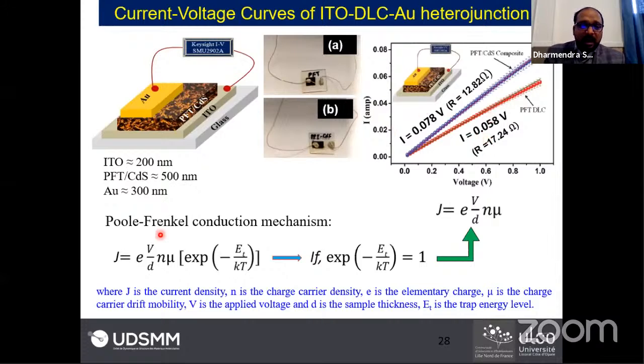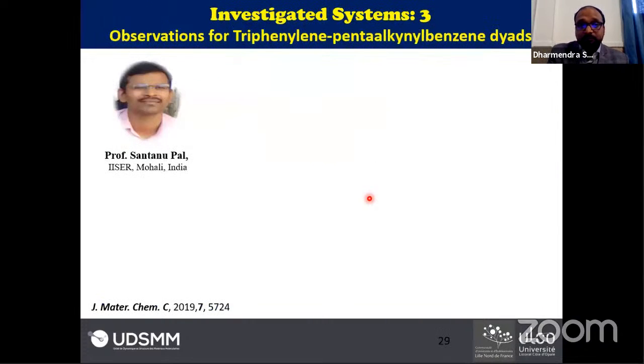Equations are mentioned here, and we found that yes, our system is following the Poole-Frenkel conduction mechanism, but under a limiting condition that this part is equal to 1. So if J is directly proportional to V, it will follow this equation, and the limiting case of Poole-Frenkel conduction mechanism is true for our system. The results are published in New Journal of Chemistry. If you want more detail, you can go to that paper, or I would love to answer your question if you have any.